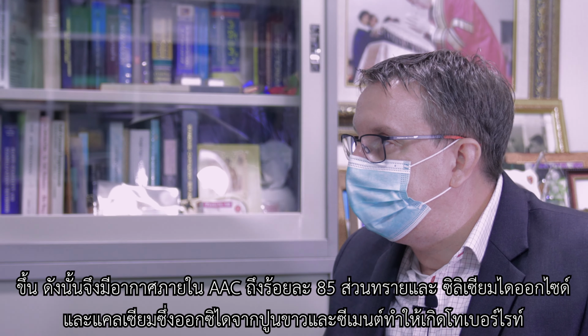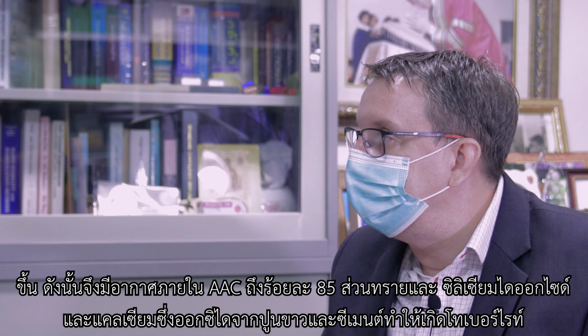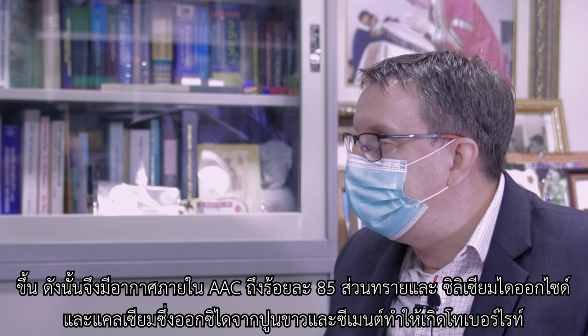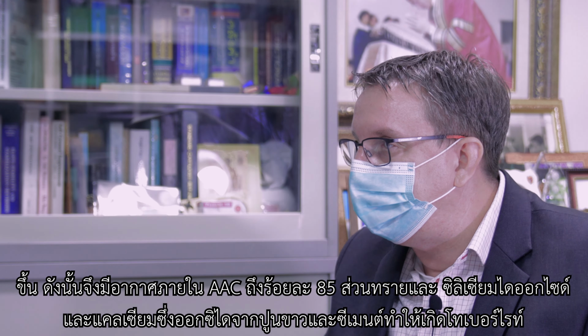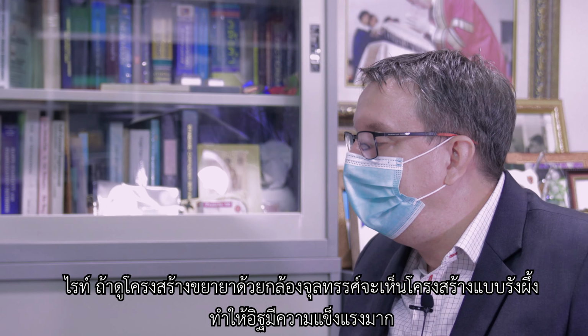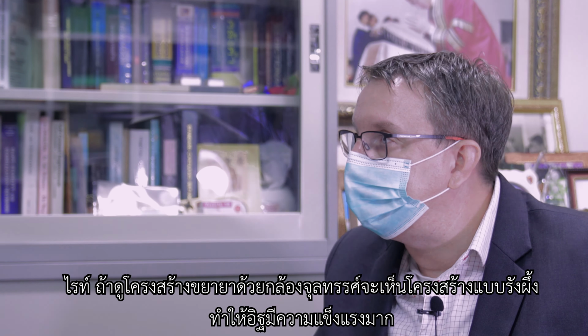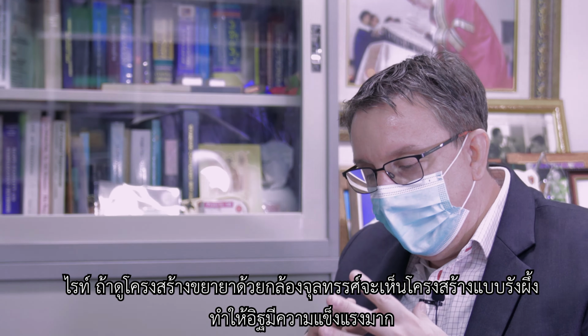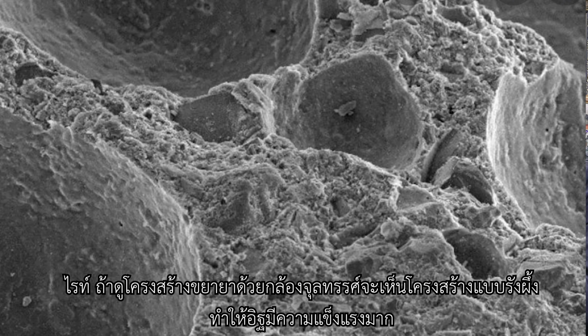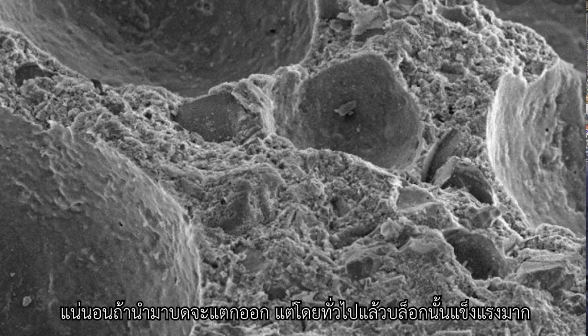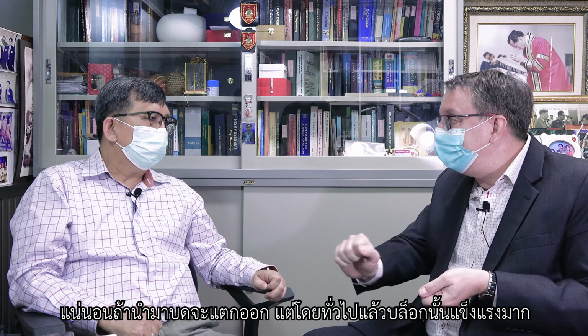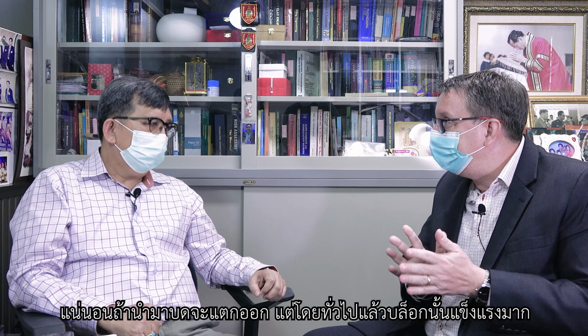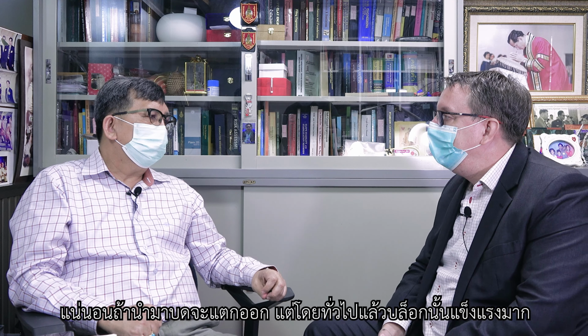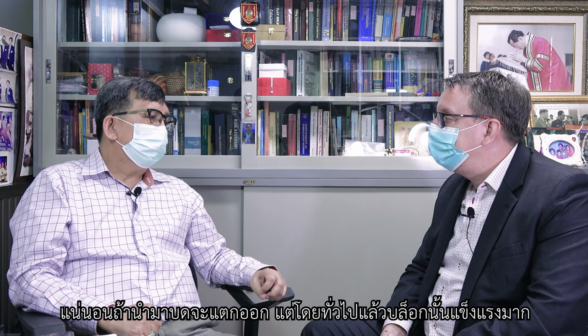And the silicium dioxide and the calcium oxide from the sand and the cement will create tobermorite. And you will see the picture where the structure on the microscope is shown. And this beehive-like texture is making the stone itself very strong. For sure, if you would grind it, it's easily going away. But generally, the blocks are very strong.